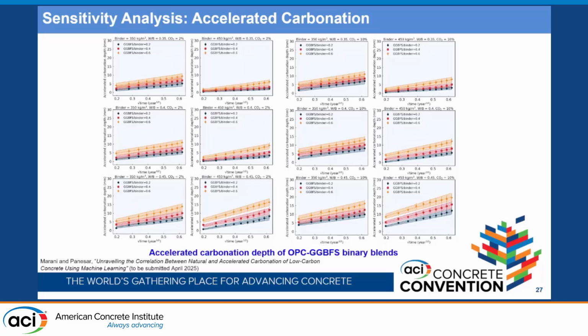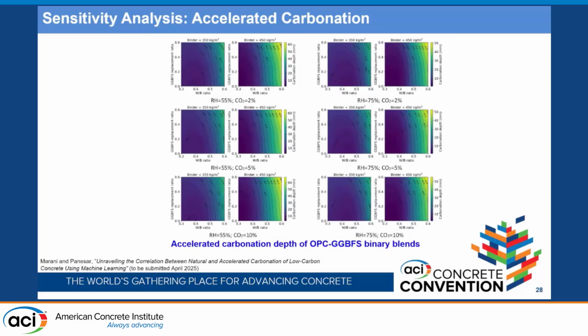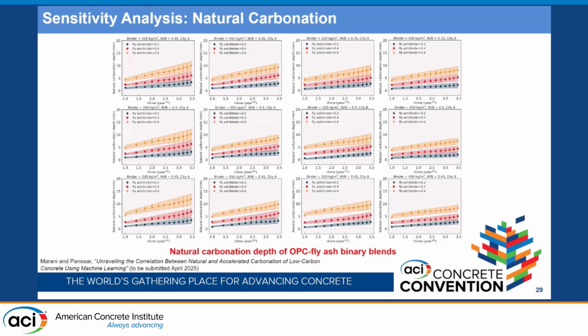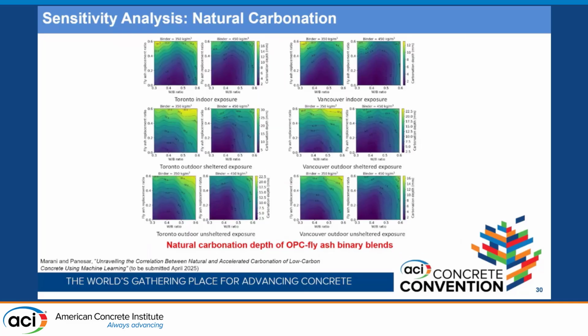For example, if we compare the fly ash and slag, we can see that the carbonation depths in slag-based mixtures are lower compared to fly ash mixtures. And again, we could have the same type of results for the slag. We also have here the results for the natural carbonation depths. So I'm going to quickly pass these slides because there are similar results. But the point here is to show that the model can capture the effects of different parameters.